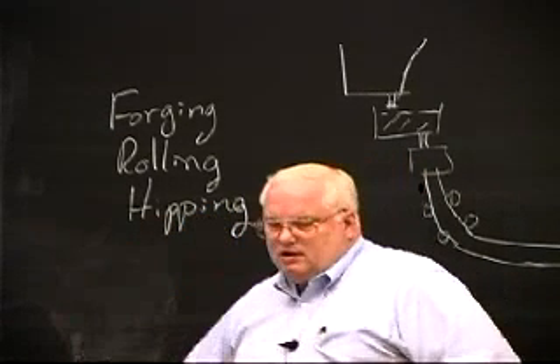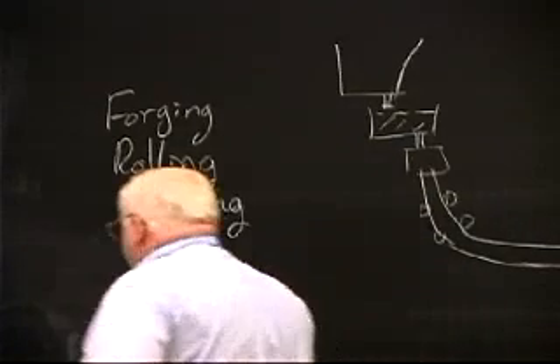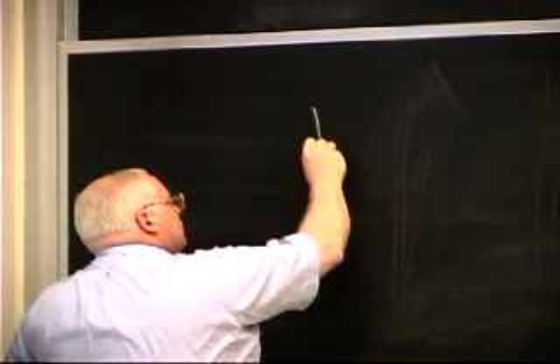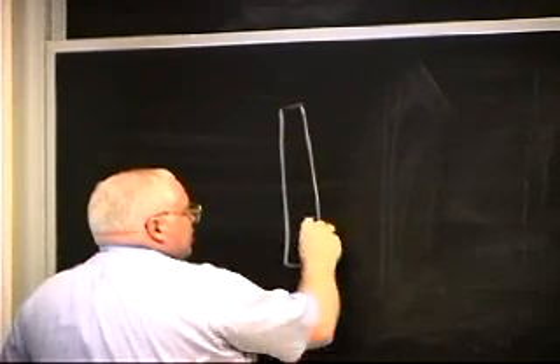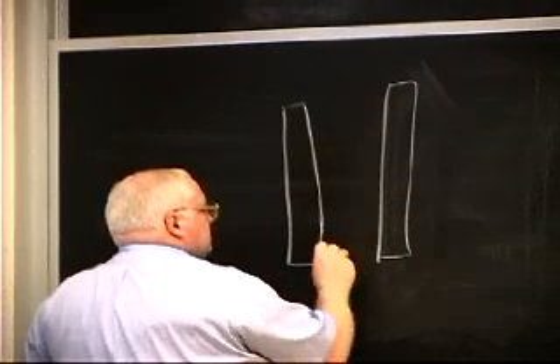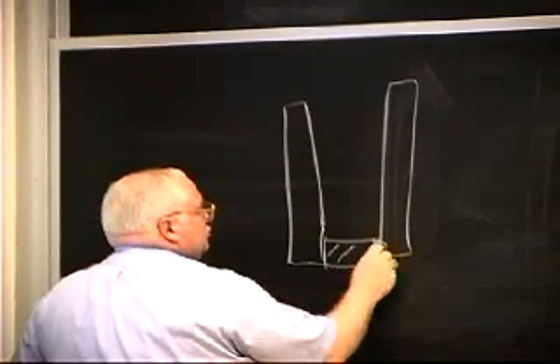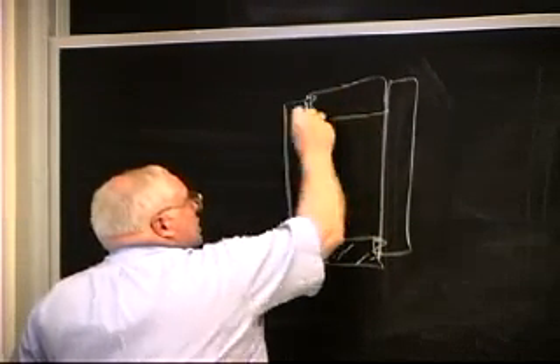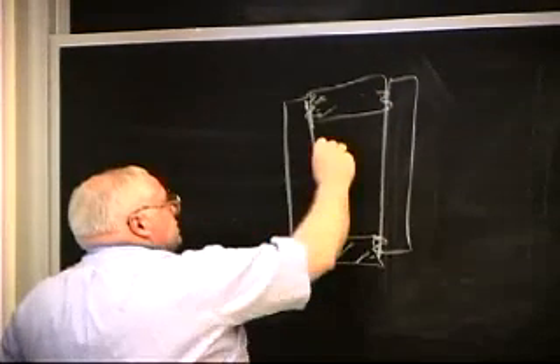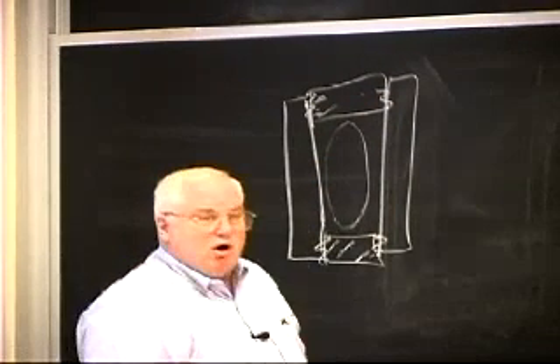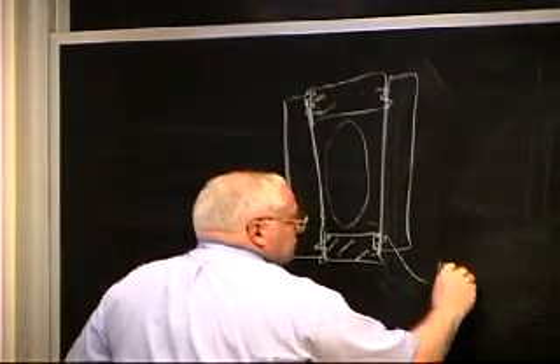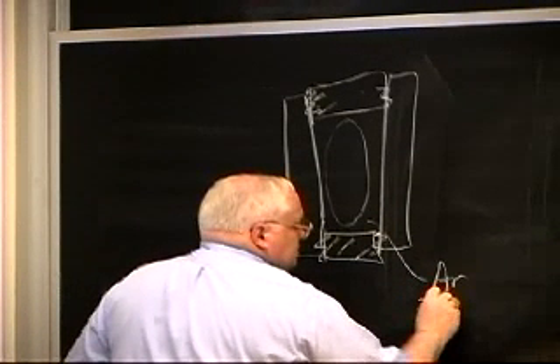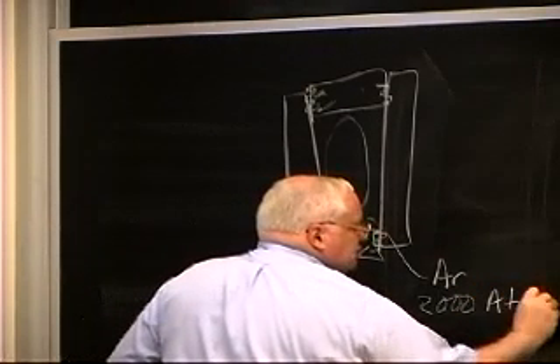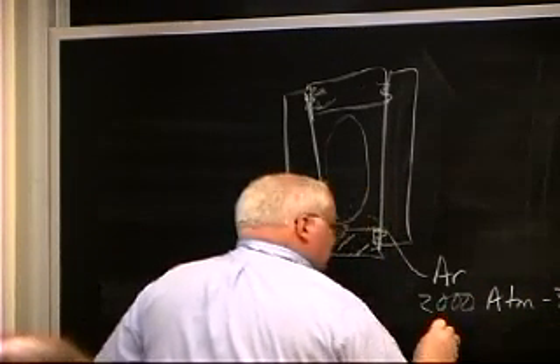Hipping is a technology that was developed at Battelle Memorial Institute, although the second one was actually in a corner of what's now my lab back around 1950. Right after World War II, to basically build a very large or very strong pressure vessel, has a screwed-in base and a screwed-in top, and I'll give you some dimensions of this in a second, and you put your part inside here, which is a gas part, and you put argon in here, and you go to about 2,000 atmospheres of pressure, which is 30,000 psi, and you can go to